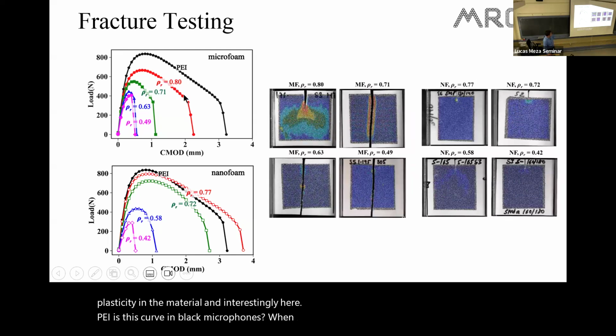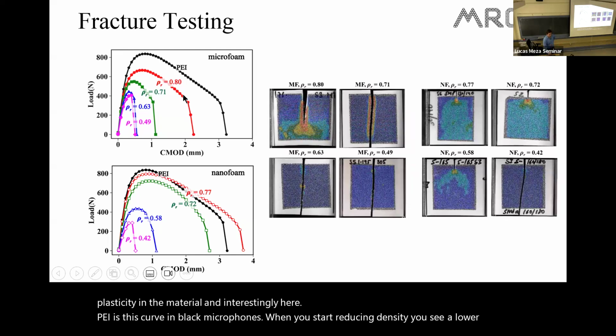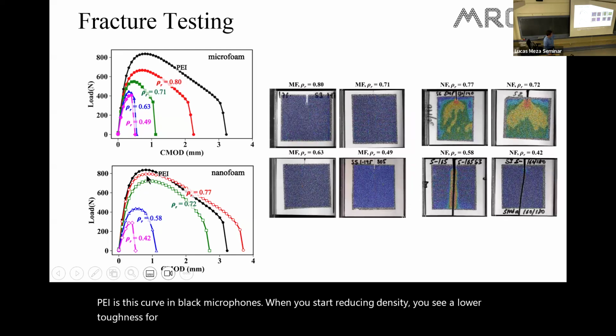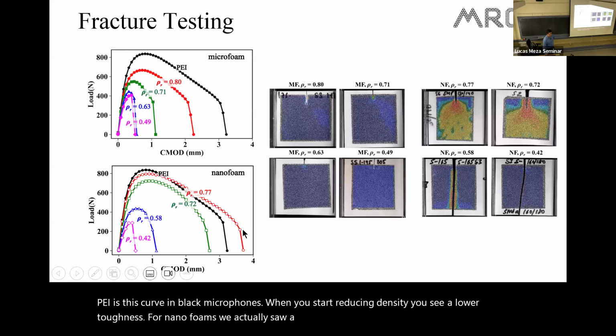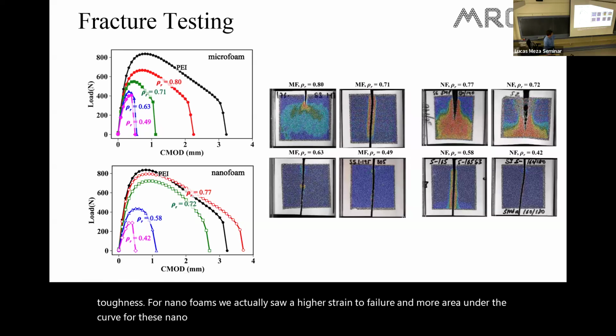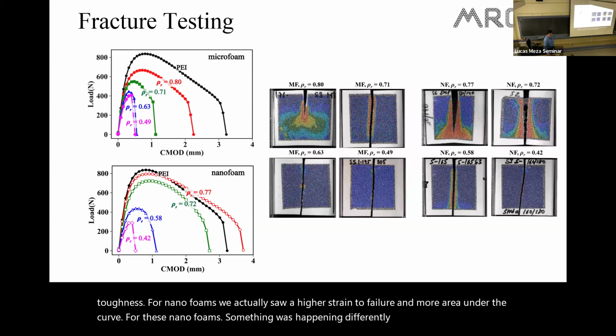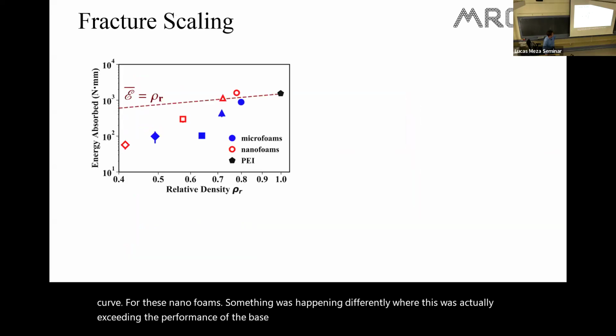Microfoams, when you start reducing density, you see a lower toughness. For nanofoams, we actually saw a higher strain to failure and more area under the curve for these nanofoams. Something was happening differently where this was actually exceeding the performance of the base material.